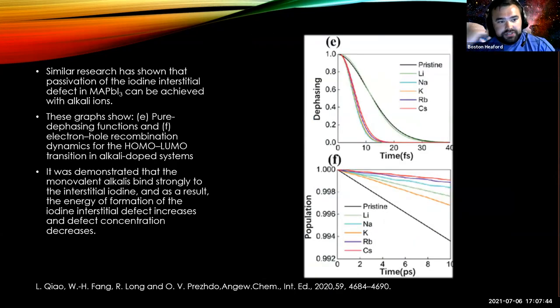And some similar research has shown that you can passivate the iodine interstitial defect in methylammonium perovskites with alkali ions. It was demonstrated that the monovalent alkalis bind strongly to the interstitial iodine, and as a result, the energy of formation increases, which decreases the concentration of the defects.